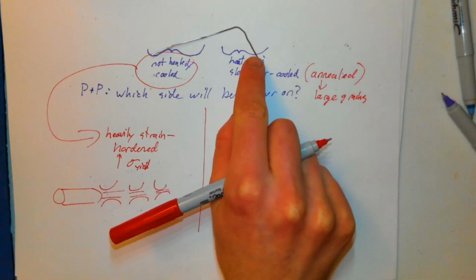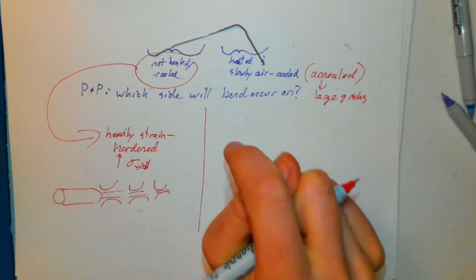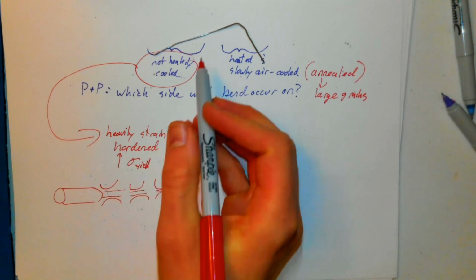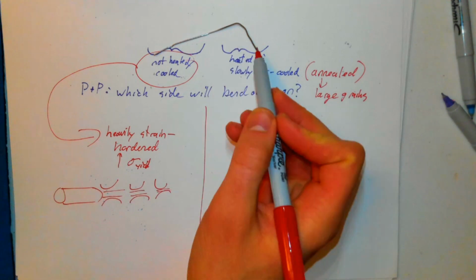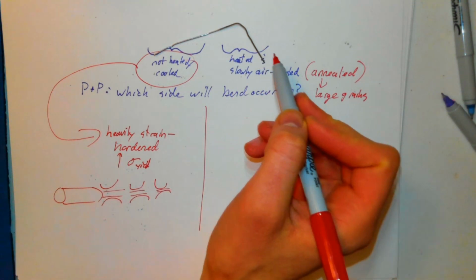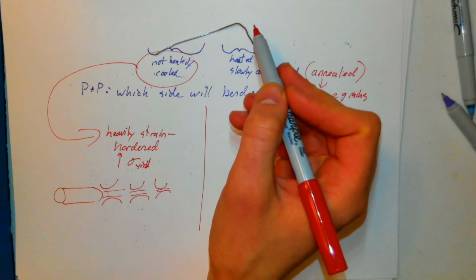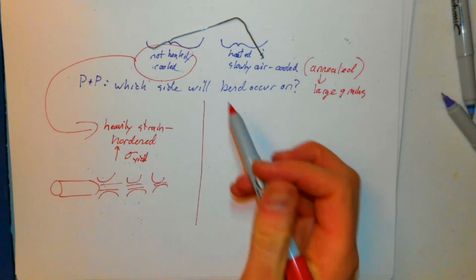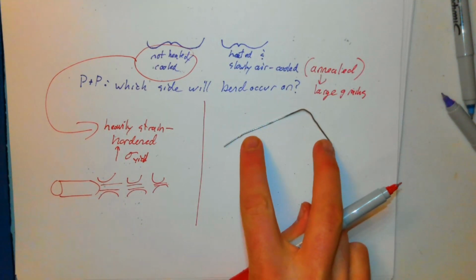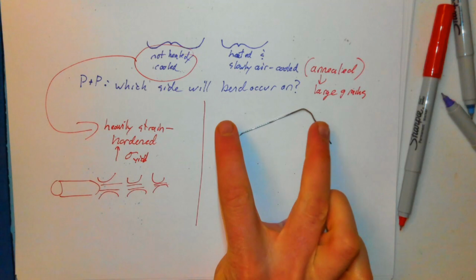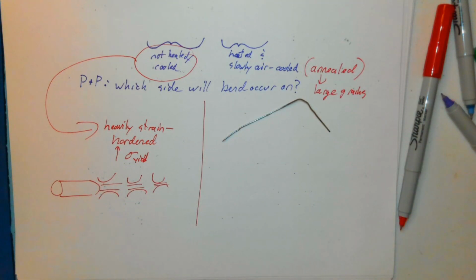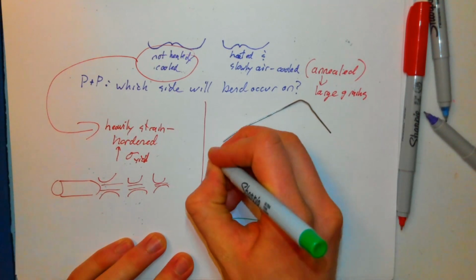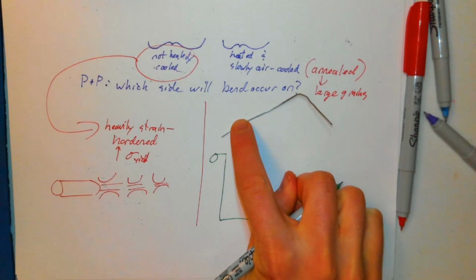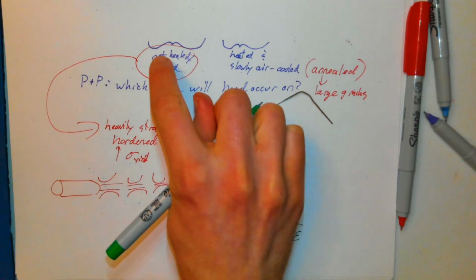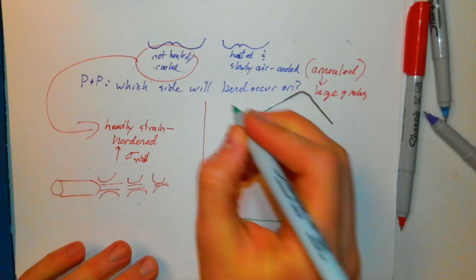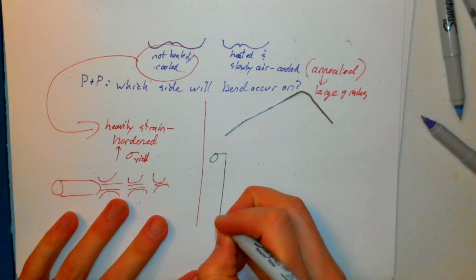So what did I do? I basically gave the heat-treated side a really lousy yield strength. This side was heavily strain hardened. I undid all of that strain hardening by heating it up and lowering its yield strength by increasing its grain size. So if we look at this paperclip now, each side of this paperclip essentially has two separate stress strain curves. The stress strain curve for the part that was not heat treated or cooled would look like this.